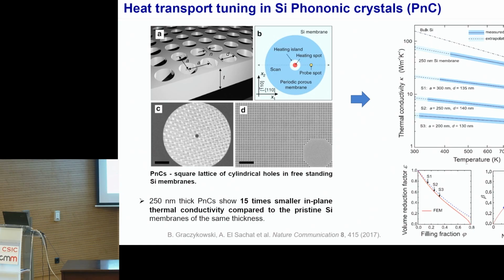And this is because we have two different mechanisms in the thermal transport when we decrease the thickness. The two mechanisms are the phonon boundary scattering, which becomes more important as we decrease the thickness of the membrane, and the phonon-phonon umklapp scattering processes. These are the resistive processes responsible for the temperature dependence. So when we decrease the thickness, phonon boundary scattering becomes dominant, so that the dependence of the thermal conductivity on temperature is smaller, and this is why this factor is decreasing. So it's telling us that the temperature dependence is no longer as significant. It's a compound effect between both mechanisms. Yes. Thank you.